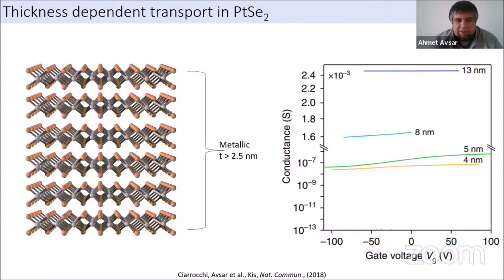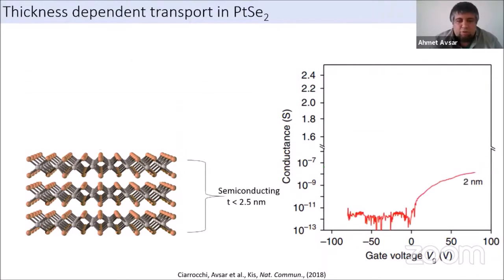So let me show you the thickness dependent electronic structure of this material, just experimental results. You can already see that if the material is thicker than 2.5 nanometers, it's very conductive. As the thickness is reduced, the conductivity starts to decrease. And as it gets thinner, it starts to respond to the gate voltage, because then you can control the carrier concentration through the electric field. But once you go below 2.5 nanometers, the material turns into a semiconductor. You can see that the material has an off current, and once you drive the Fermi level from the gap into the conduction band, the conductivity starts to increase, which is a typical response of a semiconductor.